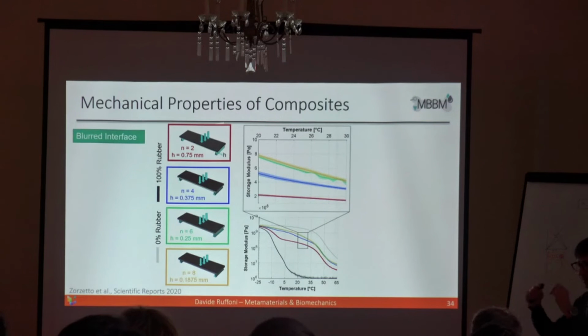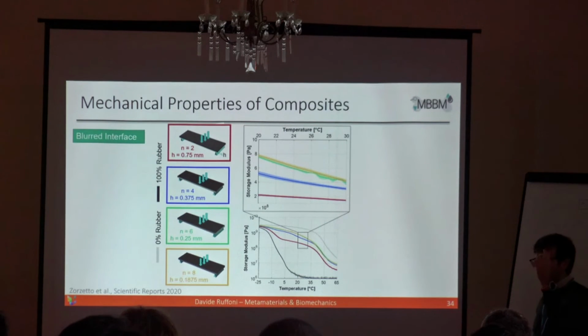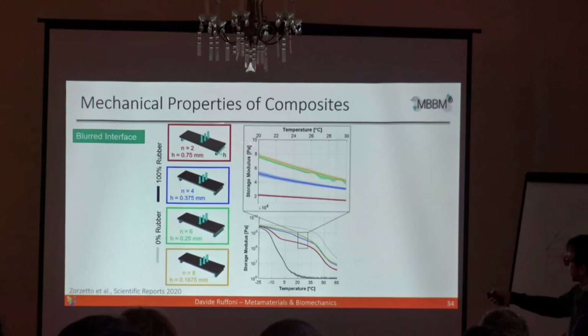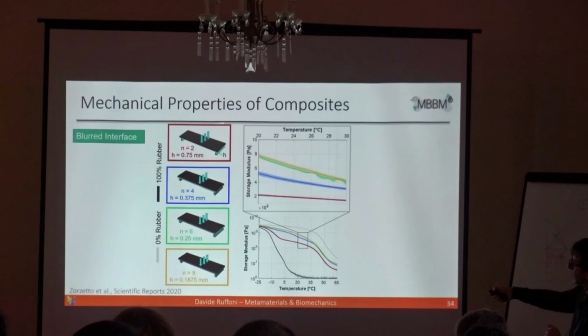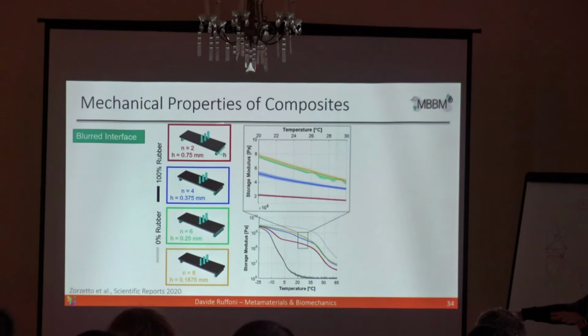And here is how it behaves when the interface between the different layers is blurred, so this 150 micrometer in thickness. What you see here is the storage modulus as a function of the different layers. Here is a system of 2 layers, so stiff and soft, 4 layers, stiff, soft, 6 layers, 8 layers, and so on.